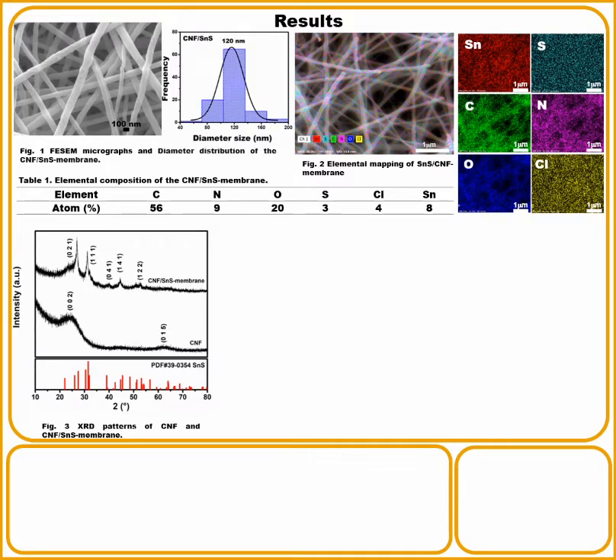Figure 3 shows the XRD patterns of the carbon nanofibers and the carbon nanofiber membrane with tin sulfide after carbonization at 800 Celsius. The carbon nanofibers had a broad peak between 2 theta of 20 degrees to 30 degrees, which corresponded to the 002 plane of graphite. However, its structure is predominantly amorphous.